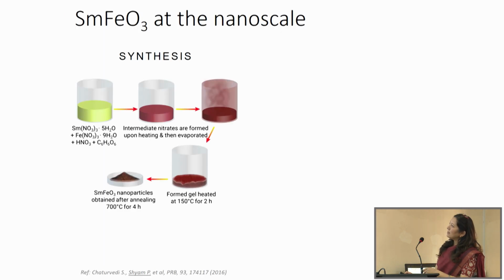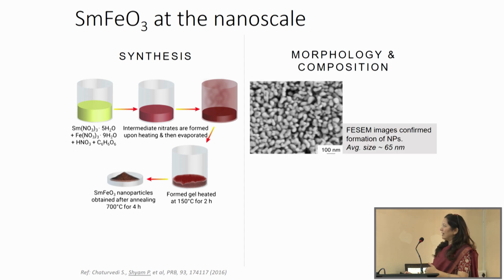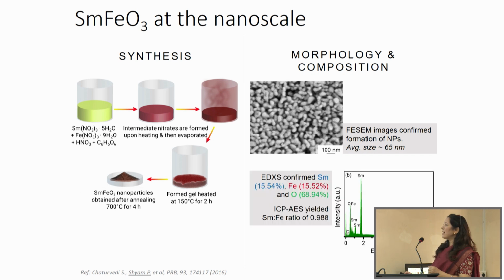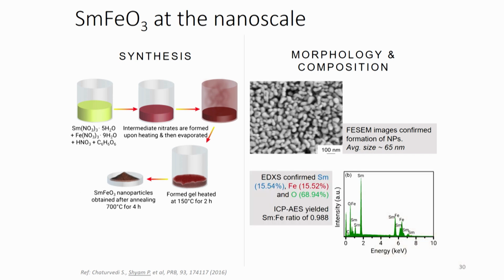So we synthesized it at nanoscale using the sol-gel method, and we prepared nanoparticles which were under 100 nanometer size, and it was confirmed about 65 nanometer average size, and we confirmed the elemental existence. Samarium, iron and oxygen were in the right proportion, so it was confirmed.